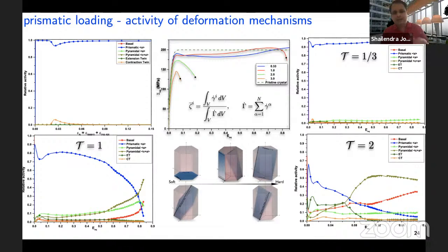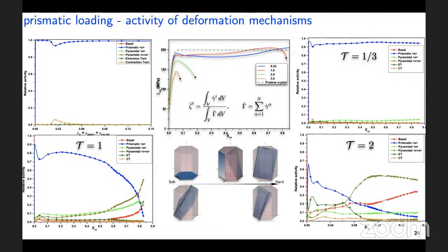So while what you're saying may be true in the context of uniaxial loading cases, it may not necessarily be true in the context of multi-axial loading cases. Generally, to say it in other words, it's quite common to see that with increasing triaxiality, the strain to fracture drops quite rapidly. Right. Yeah, thank you.